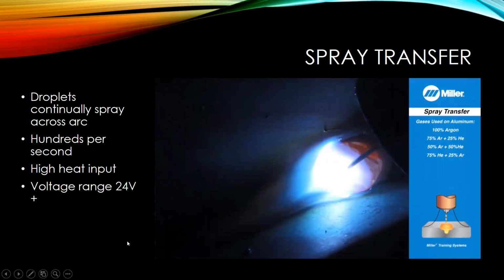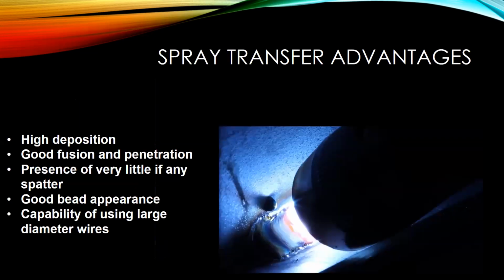So spray transfer isn't typically used in auto collision, but I kind of want to talk about it a little bit because spray transfer is used in industry a lot, but it's usually used towards thicker plate, like 1/8 inch or thicker. Good thing about it is you get high deposition rates, so you transfer a lot of metal quickly. It allows you to travel fast, and because you're never shorting, there's little to no spatter. You can also run large diameter wires.